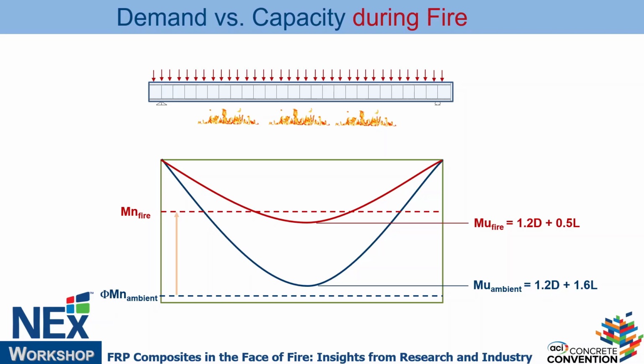But if I'm doing strengthening, I'm adding what? Dead load and possibly live load, right? Or live load and possibly dead load. So I'm increasing the demand. When I increase the demand, I lower the fire rating. That's why, within 440 and 562, we're thinking we need to address the fire, because when you increase the loads on existing geometry, you're basically playing with the fire rating. You're reducing it, and you have to address it somehow, and we need to run calculations. If, again, the capacity I found is lower than the demand, the load factor demand during fire, which is 1.2 dead, 0.5 live, that means I need fire protection.